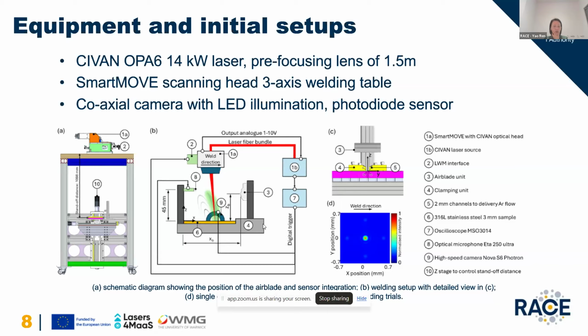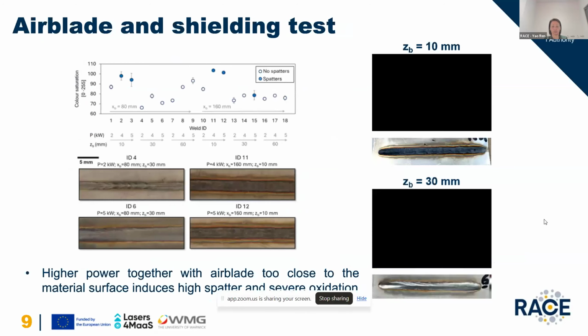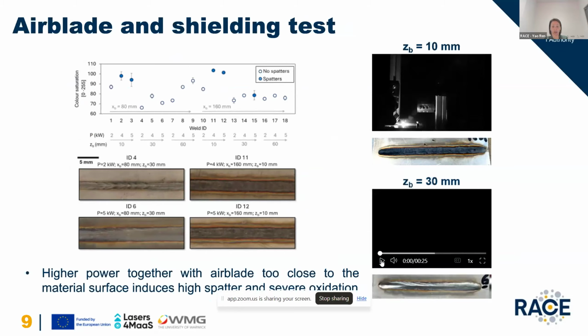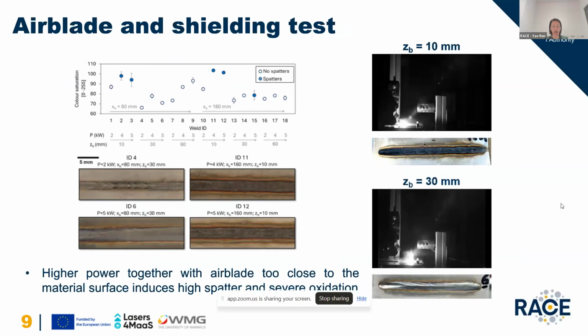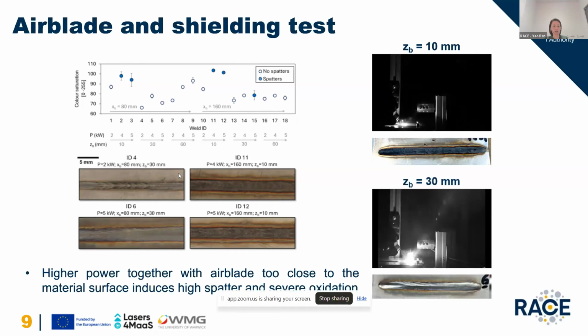The first thing we tackled was to design and set up how we want to shield the molten pool and how we actually use the air blade to ablate the plume generated during the process. Some initial studies gave us some suggestions. It was found that a higher power together with the air blade too close to the material surface induces high spatter and severe oxidation. And this is the comparison of how close and how far away we set it in the Z direction, meaning the vertical direction, and how that impacts the process. You can see the surface is severely oxidized when it's too close.